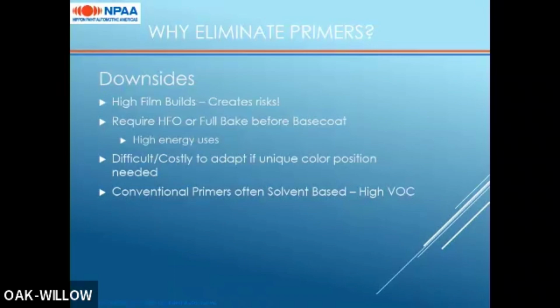Most lines try to limit the number of primer systems that they have, which then means that any colors you adapt to go over those primers either need to have a unique primer developed for them or have to be adaptable to the primers that exist. With this system, there's still a need for multiple basecoat systems, but it's easy to adjust those basecoats for the color positions that are needed. Additionally, conventional primers are often solvent-based, which is high VOC. This system is water-based for both base coat layers, which helps reduce VOCs.